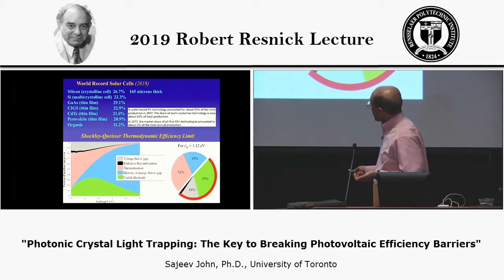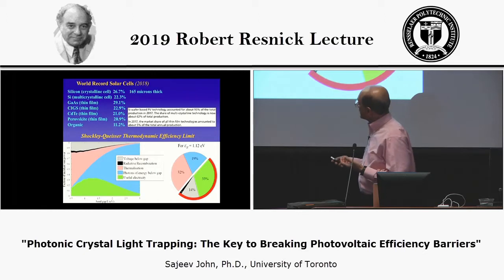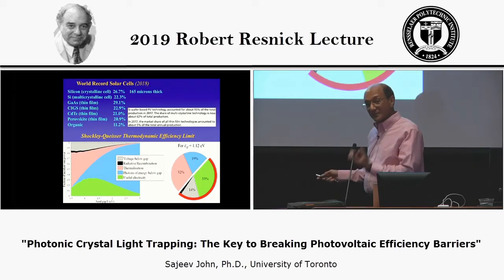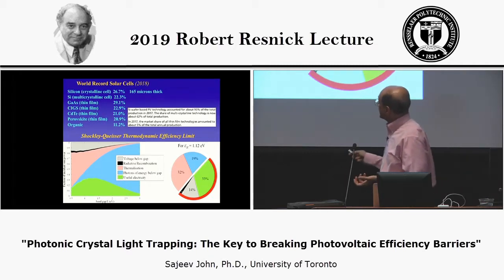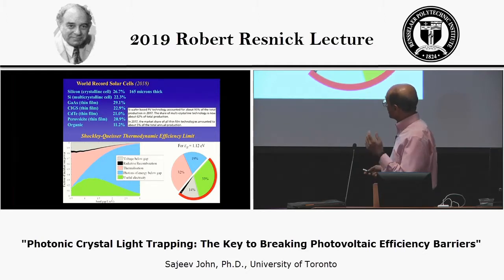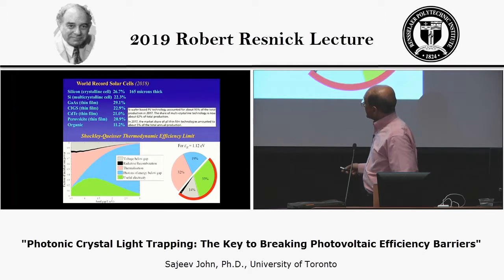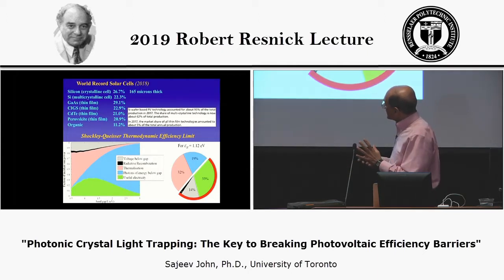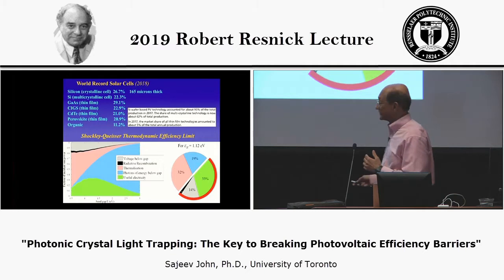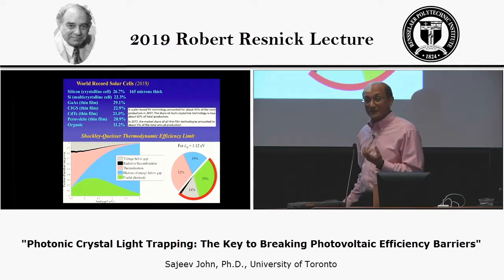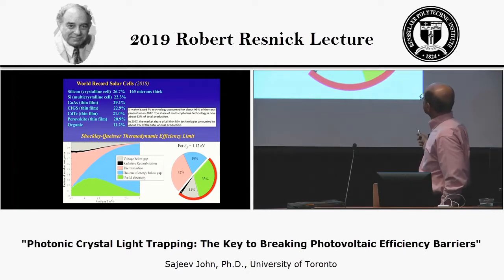On the other hand, if you make the band gap larger, there's less of that thermalization loss, but this blue region depicts the range of energies where the sunlight falls below the band gap and it's not absorbed at all. So this is not being converted, it's just being reflected or transmitted without being used. And Shockley and Queisser considered the balance between these two effects and discovered that the optimum occurs somewhere around here, band gap energy between 1.1 and 1.4 electron volts, where both silicon and gallium arsenide lie, which would have the maximum possible efficiency. So here I show a chart for the maximum possible efficiency of a silicon-based solar cell with a band gap energy of 1.12 electron volts.